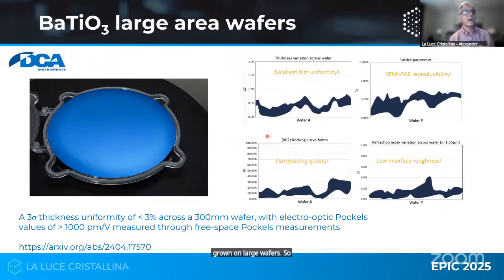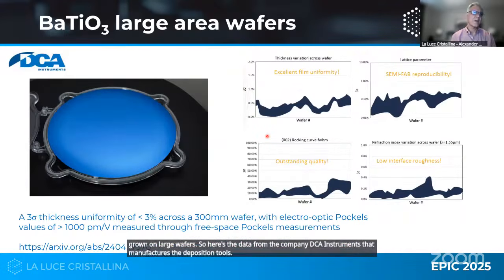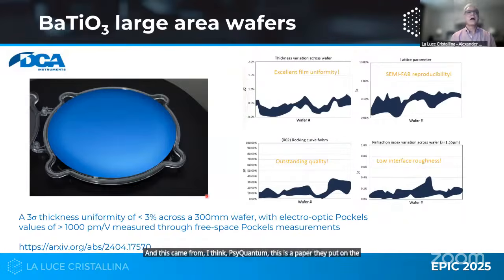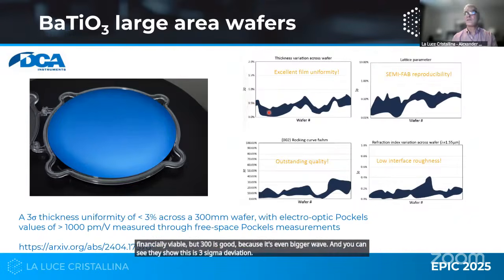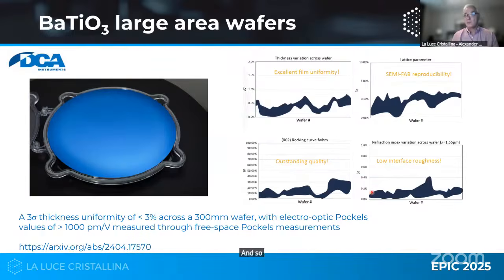So here's the data from the company DCA Instruments that manufactures the deposition tools. And this came from, I think, PsiQuantum. This is a paper they put on arXiv. And this is the uniformity data on a 300 millimeter wafer, right? So 300 millimeter. Remember that we're just barely touching where 200 millimeter is financially viable, but 300 is good because it's even bigger wafer. And you can see they show this is a 3 sigma deviation, excellent thickness uniformity across the wafer. Lattice parameter doesn't change. Rocking curve, that's the quality of the Fourier transform of the real space lattice, is very good. And so refractive index also doesn't change very much, and they claim the Pockels coefficient in the order of 1,000.